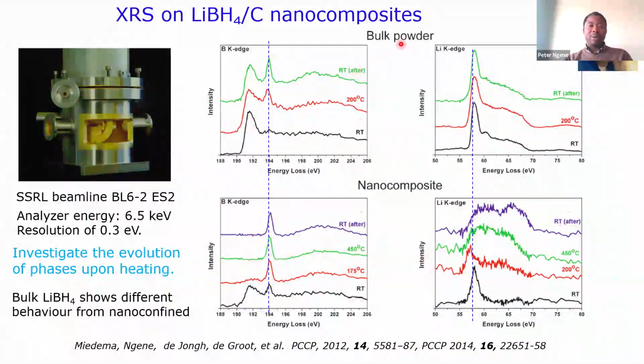So in this case it is the bulk powder. So this is the lithium borohydride. And this is how it looks at room temperature. If we heat the sample up, you begin to see another peak appearing here. And then if we cool it down again to room temperature, we do see this same peak again. So we couldn't go to higher temperature that time, because there are a lot of complications, there's melting, and so it wasn't successful.